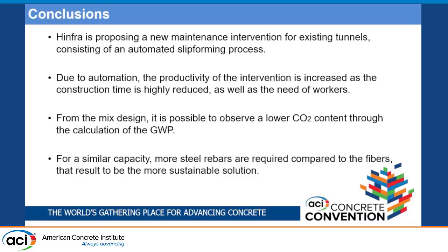So going through the conclusions, Hinfra is proposing a new maintenance intervention for the existing tunnels, consisting of an automated slip forming process. Due to the automation, the productivity is increased and the number of workers can be reduced. From the mixed design, it's possible to observe a lower CO2 content through the calculation of the GWP, and for a similar capacity, more steel rebars are required compared to the fibers. That results in a more sustainable solution, the one made by Hinfra.